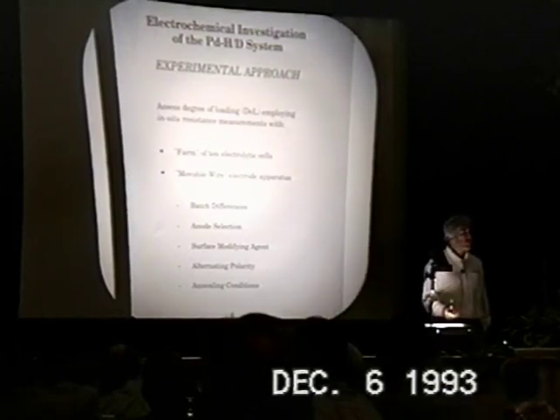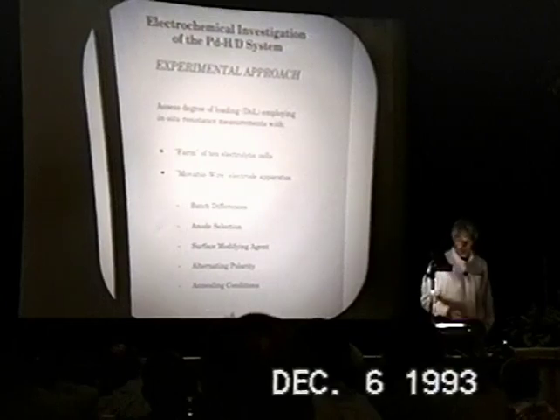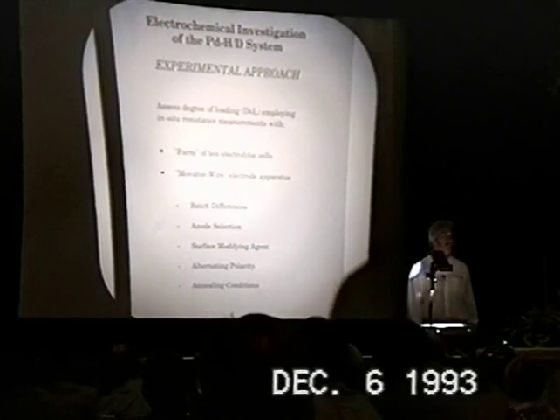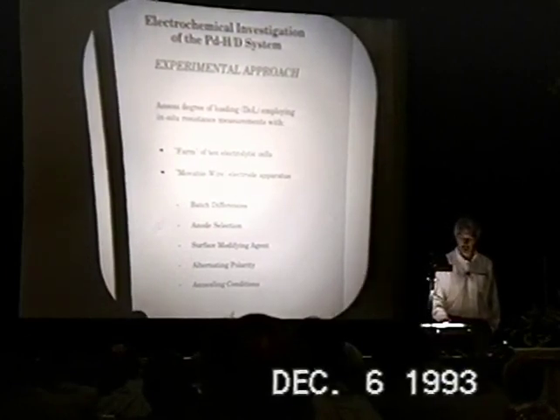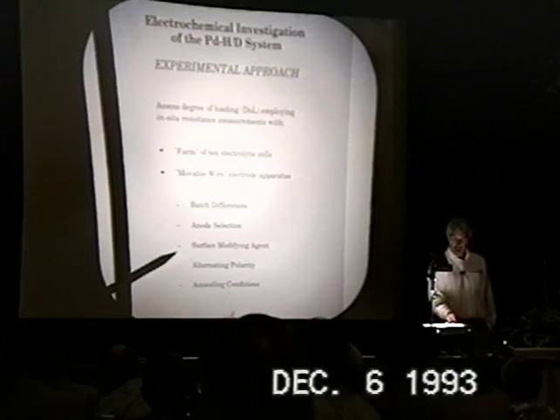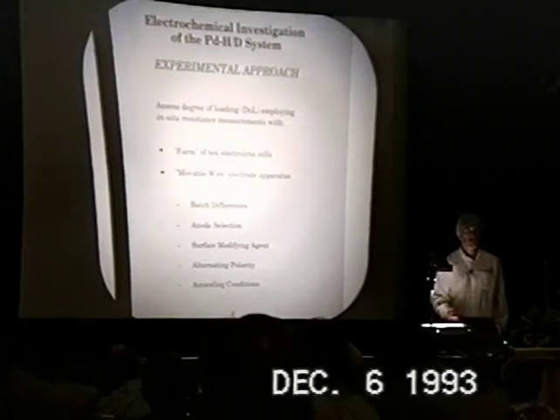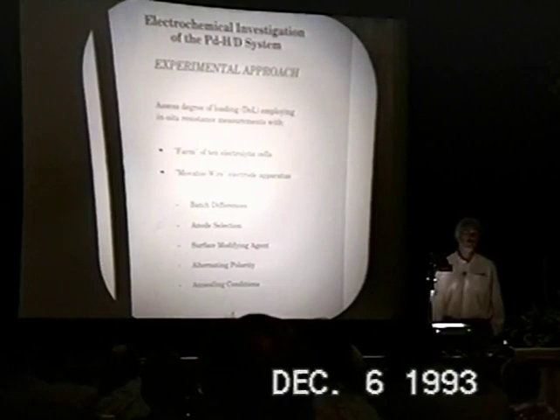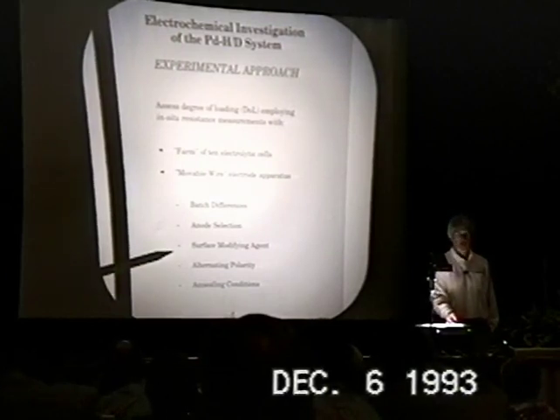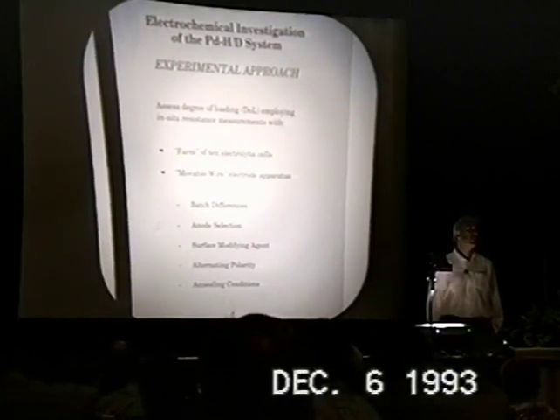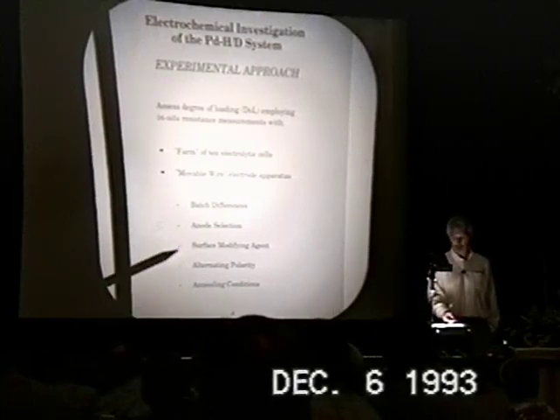The differences which have already been mentioned before by the previous speaker: the difference between different batches, different lots of palladium from the same supplier, nominally identical. Anode selection, and surface modifying agents, where we have used and found successful additions of aluminium and silicon, which form aluminates and silicates in the electrolyte, and the role that this plays in